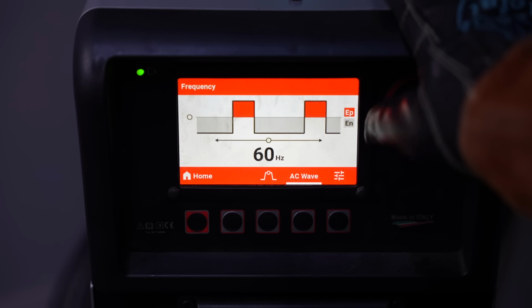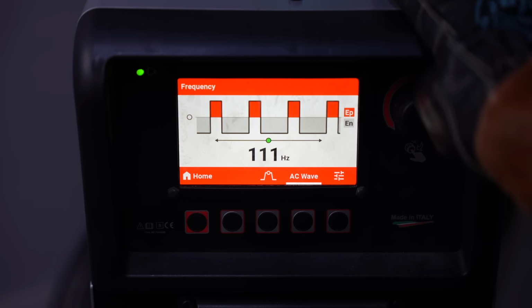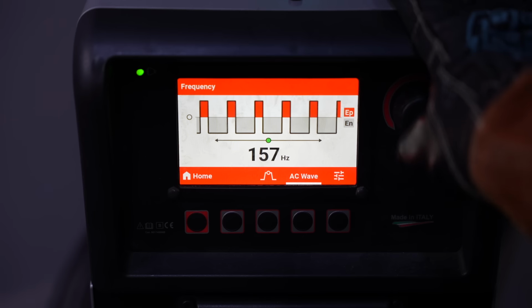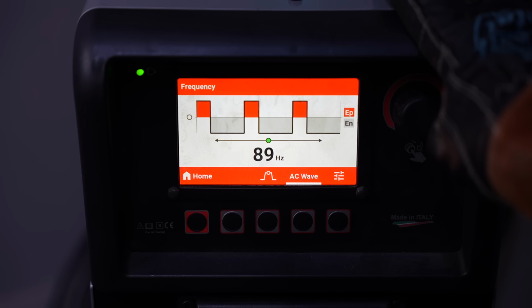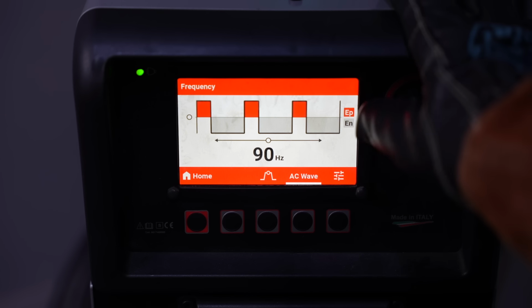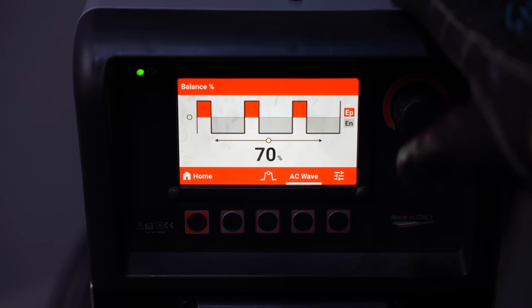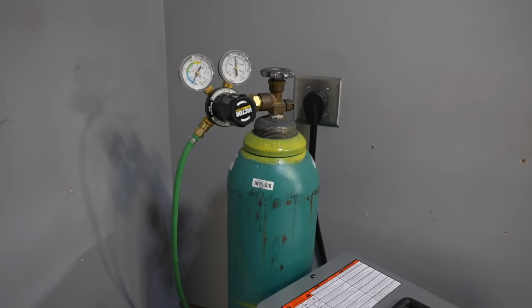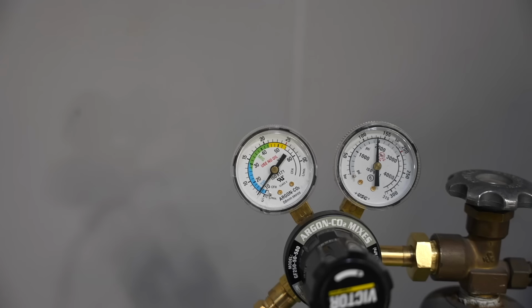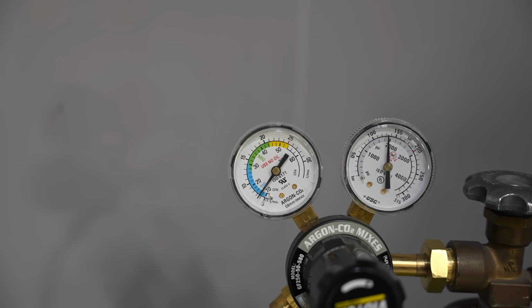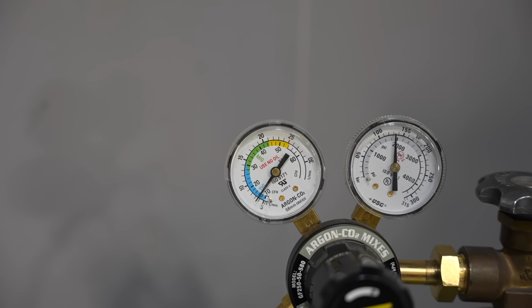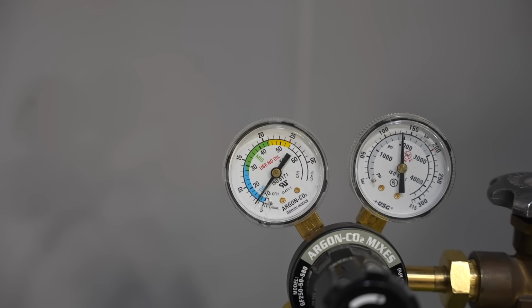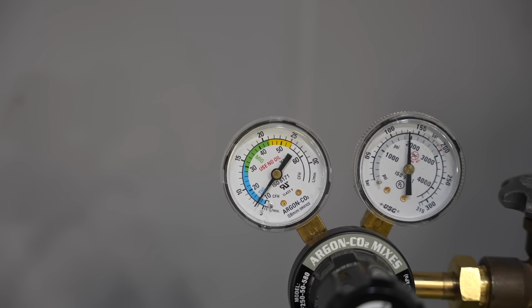Then frequency is how fast that happens, right? So I'm gonna set this right to 90 Hertz. Anywhere between 60 and 120 should work just fine for you. As far as shielding gas, I'm running straight argon here, and my gas flow rate is set to about 2.5 times my cup size. And so for a number 5 cup, I'm right around 12 to 13 CFH.